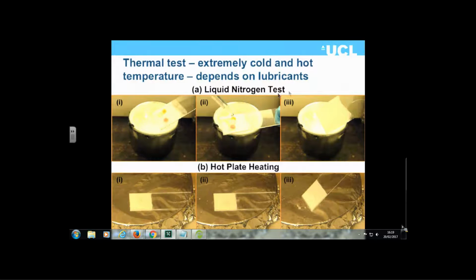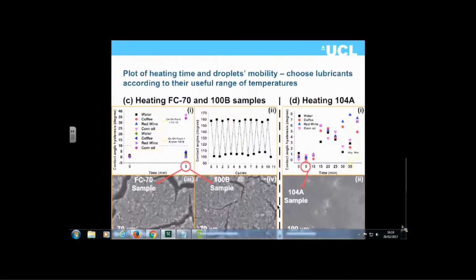So this is an example here with some liquid nitrogen testing where we took our liquids, froze them into liquid nitrogen, took them out, let them warm up, and then they dropped off the surface. Similarly, you can put them on a hot plate at 200 degrees C and it also recovers its properties.